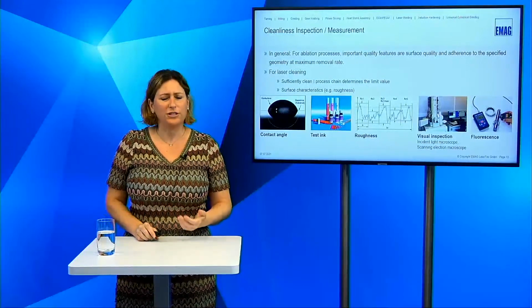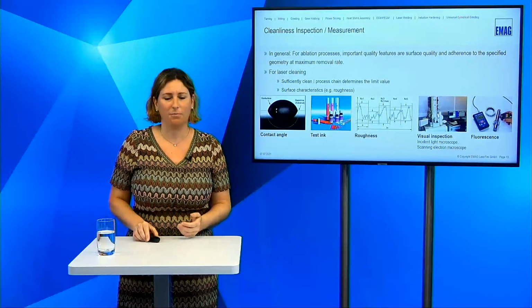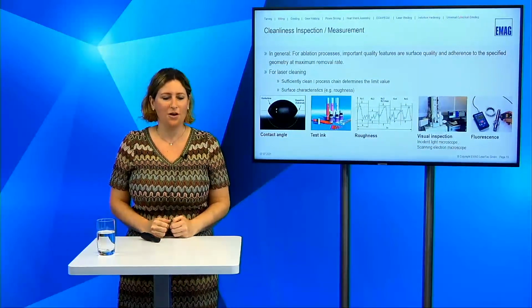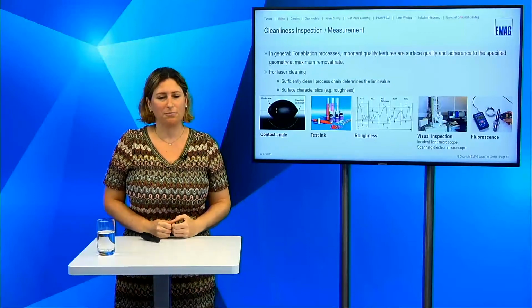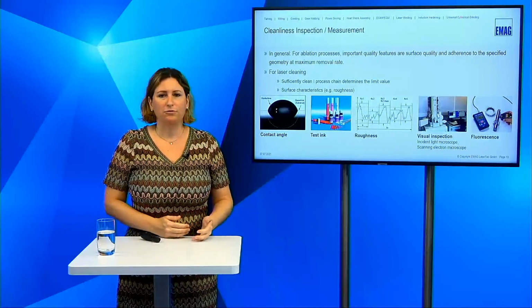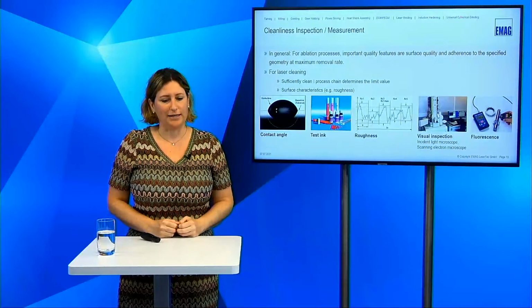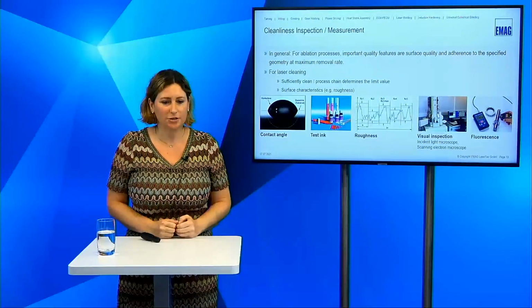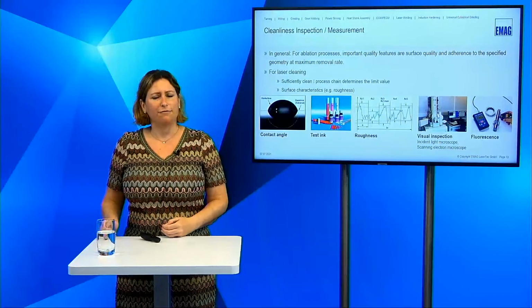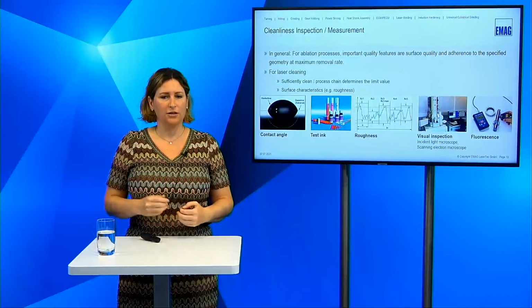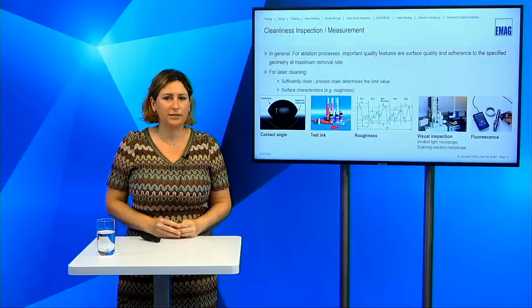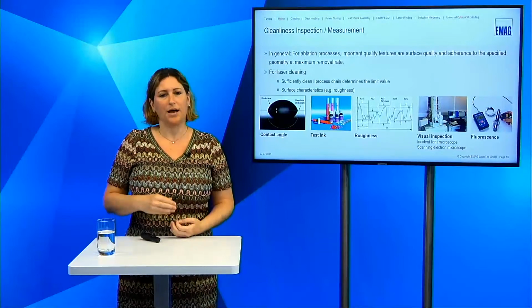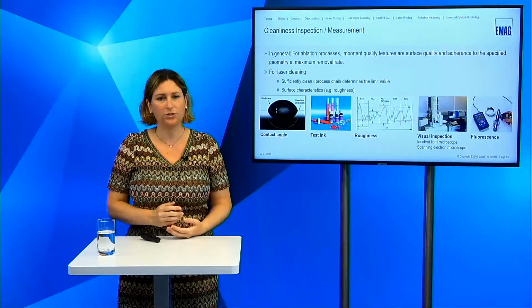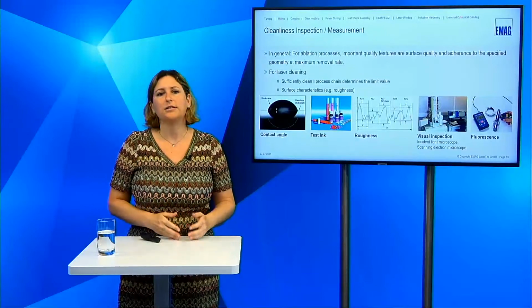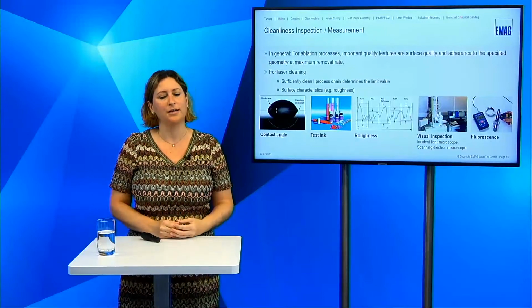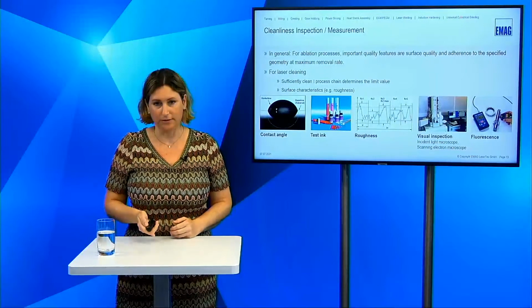You can also use visual inspection by eyes or by incident light microscopy or in more detail electron microscopy. This works quite good, for example, for phosphate layers. And you can use fluorescence measurements. They work really nicely for liquid contaminations. So when there's a liquid on the surface, it starts to fluoresce under this system. And the more liquid is on it, the more fluorescence will happen, and the higher the value will be.